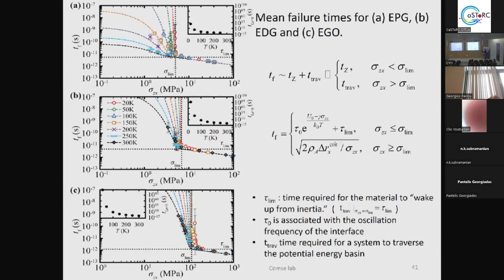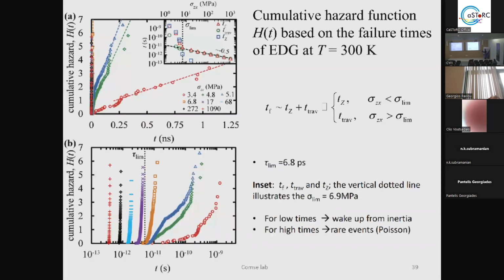But as we put bigger stresses like this one, the slopes become more and more sharp, like the second plot that we have here, which, as I told you, is a zoom in on the very small times. And as we put bigger and bigger stresses, we have a totally sharp slope, which depicts that the probability of failure is 100%. The failure will happen directly. That's why you can see very small times. It means that as soon as you put brute stresses, the failure will happen directly, very, very fast.